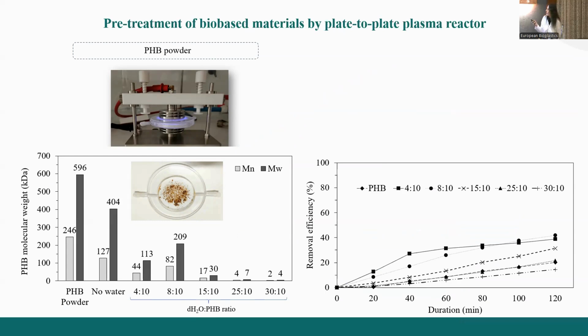Regarding the pretreatment of PHB samples, we employed a plate-to-plate plasma reactor, and we evaluated different moisture contents in the sample. So the hydrolysis, the degradation efficiency of PHB was evaluated regarding the reduction of the molecular weight of the pretreated samples. And we observed that the higher the moisture content, the lower the molecular weight of the pretreated samples.